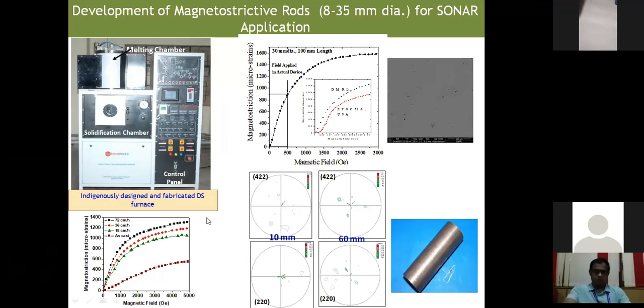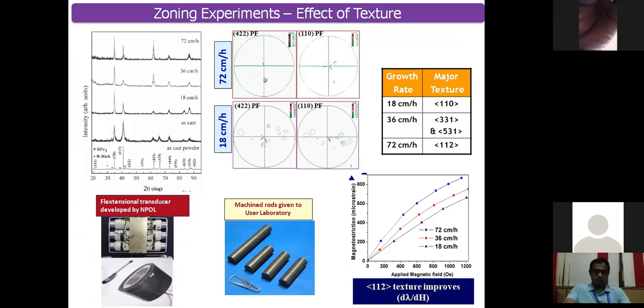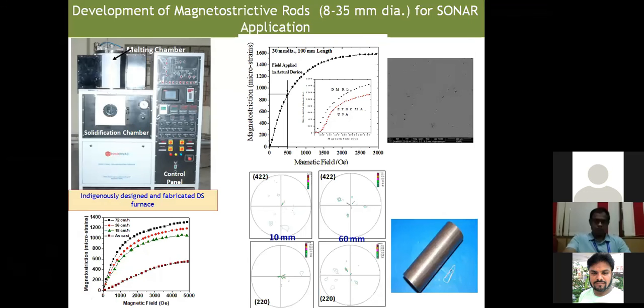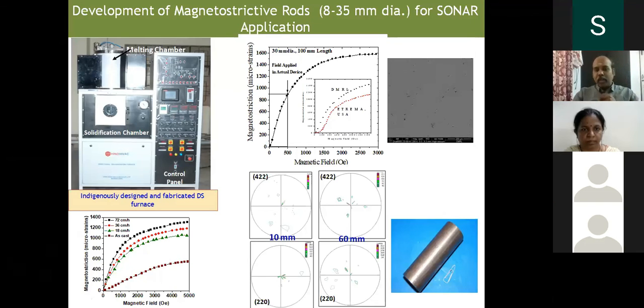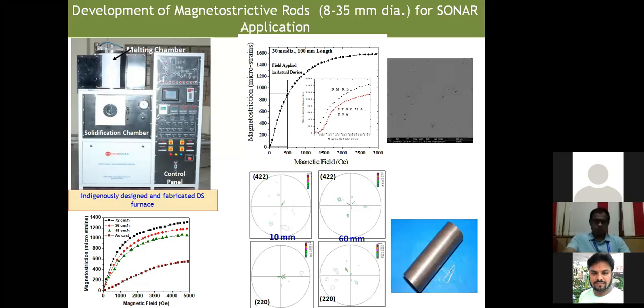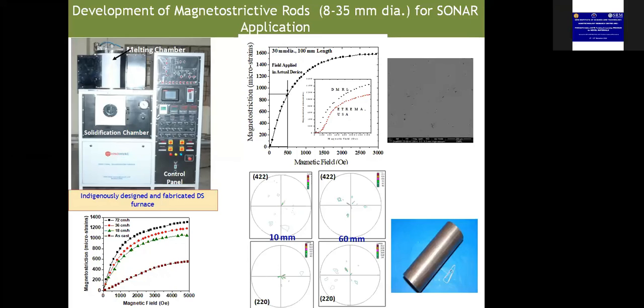So the magnetostrictive rods which I have developed earlier, which are shown, are only 8 mm diameter, but our sister laboratories require magnetostrictive rods up to 30 mm diameter and up to 80 mm long. So there is a requirement to have bigger diameter rods, but there are a lot of challenges when we scale the material. For example, an 8 mm rod is only some 50 or 60 grams, but a 30 mm diameter rod is 1 kg. So there is a huge challenge when we scale it up.